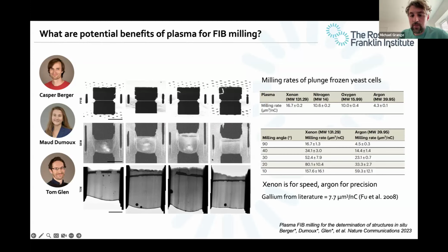And you might think, well, why would we use argon? Well, I just showed you, hopefully, that we can produce flatter lamella with argon. So we were using that case. So we were really using the flat aspect. We were being careful in this experiment. We didn't want to move fast, but obviously there is room at the top for xenon to try and increase the speed of this milling rate.